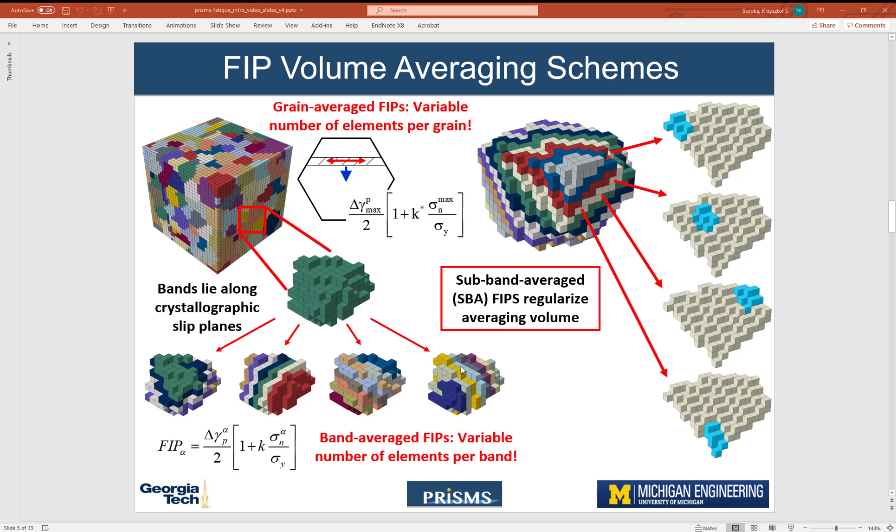The final scheme simply takes these elements and assigns them to smaller regions called subbands. So the main reason to do this is that the subbands are equivalent in volume.